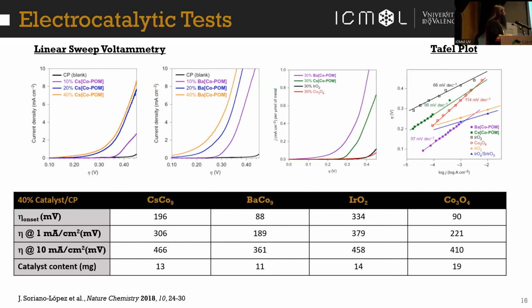So basically, you will have a straight line coming from the beginning of the catalytic reaction. From the slope of this straight line, you get information about the kinetics of the reaction, and it also tells you some of the mechanism that the catalysts are following. I don't know if you can see it here, but both Co-POM electrodes showed a very similar slope, and the cobalt oxide shows a much higher slope, which is typical for cobalt oxide. So this is another proof that we do not have cobalt oxide in our electrode. We also compared it with iridium oxide, which gave typical values for iridium oxide. And again, the barium salt of the Co-POM was even better than the most active iridium-based material reported at that time, at least for low overpotentials.